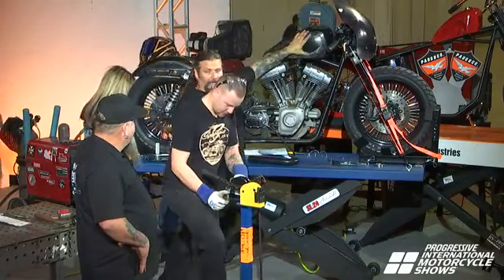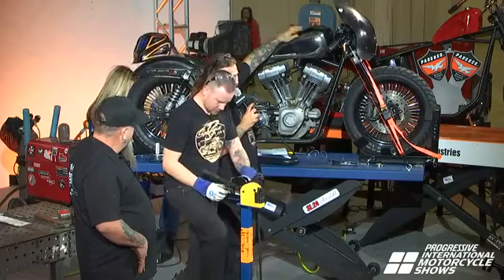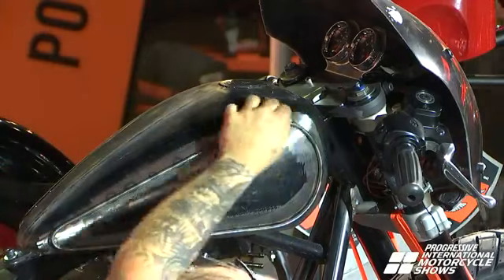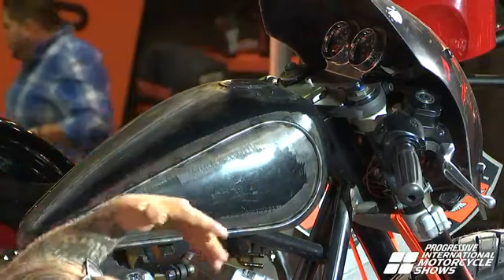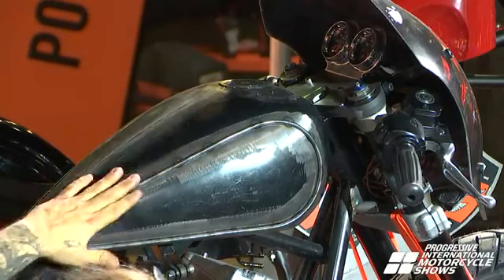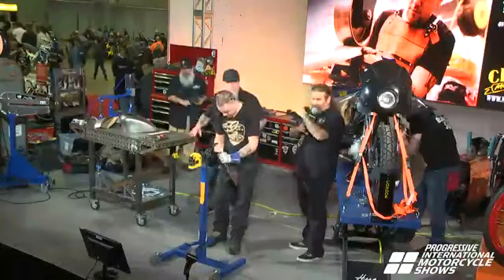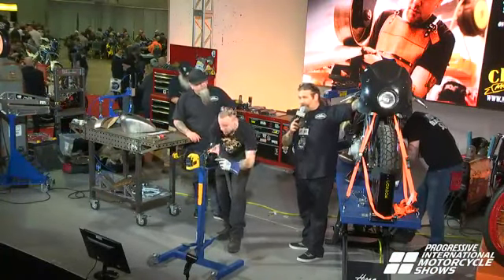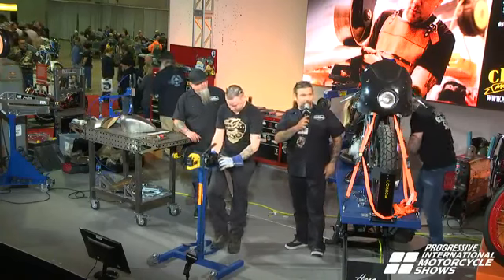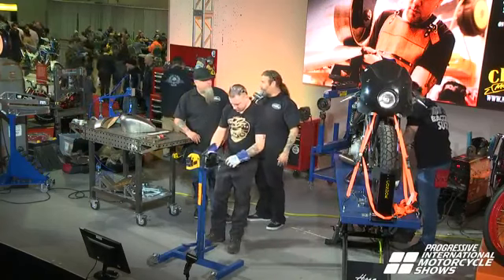But for me, I'd leave this like this, and then come back in, and in the corner of that tank, I'll run silicon bronze with the TIG welder. It's a trick a lot of the hot rod body guys are doing. You fill that whole thing in with silicon bronze and then come back in. The bronze comes out a lot easier than the parent metal, so it lets you work it almost like a putty, but it's metal. So it's never going to go anywhere. You don't have to deal with it like you do with auto body filler. You end up with a nicer product. Of course, you could go through the whole thing of lead soldering, but the silicon bronze is a nice, quick, easy trick. It'll come out nice and smooth, and it'll pretend that I'm a much better fabricator than I am.